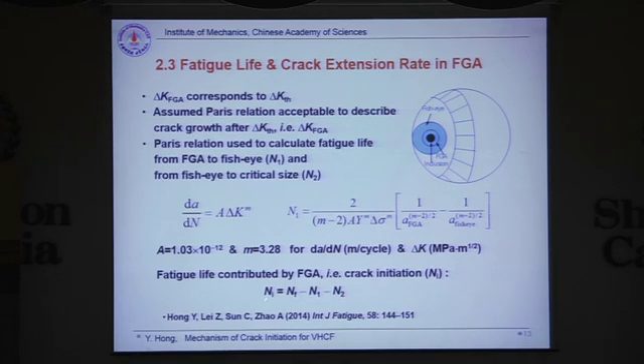The idea is that the life for initiation is the total number of cycles minus N1 and N2. N1 is from the FGA boundary to the boundary of the fisheye, and N2 is from there to the final fracture point. We have the total fatigue life, or the loading cycles, and if we can get N1 and N2, then we can get the life for crack initiation. We use the Paris relation to obtain N1 and N2.